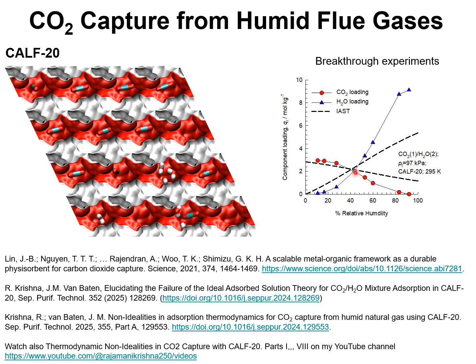For values of relative humidities lower than about 45%, the adsorbed phase is poorer in water and richer in CO2 than anticipated by the IAST. This is due to the segregated nature of adsorption, wherein the CO2 molecules and the water molecules are not located at the same adsorption sites within the channels of CALF-20.